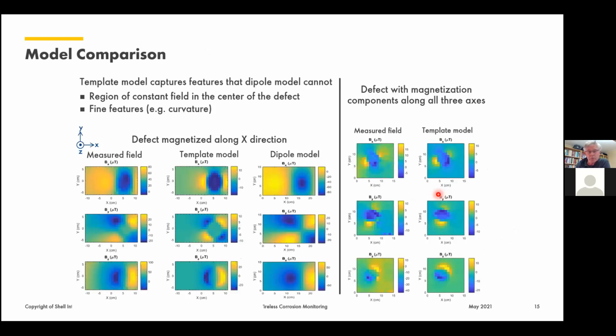So here a few comparisons. I don't want to bother you too long with these pictures, but I will limit myself to the information on the left side. In this column we have the measured field Bx, By, and Bz, and the middle column is the matched template. If you compare the measured field and the template, you see a reasonable correlation also in the size of the dipole field.